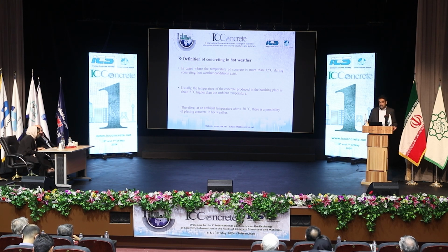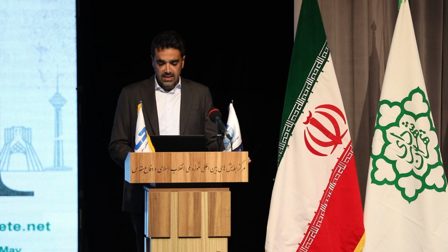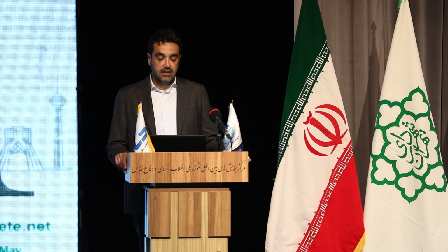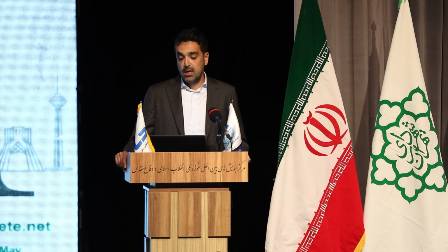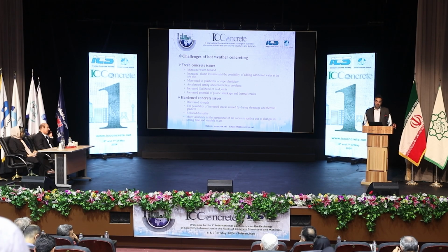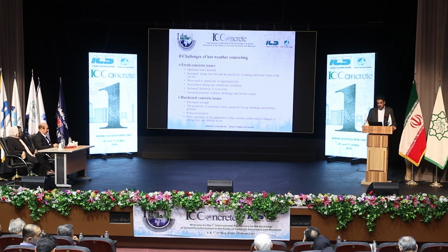All of us are familiar with the definitions of hot weather concreting and cold weather concreting, so I skip these slides. As you know, we have challenges when concreting in hot weather. Some of them are associated with fresh concrete issues, and some with hardened concrete issues. For example, in hot weather concreting, we face increased water demand, increased slump loss rate, and the possibility of adding additional water at the job site, or more need for superplasticizer, accelerated setting and construction problems associated with it, increased likelihood of cold joints, and increased potential of plastic shrinkage and thermal cracks.